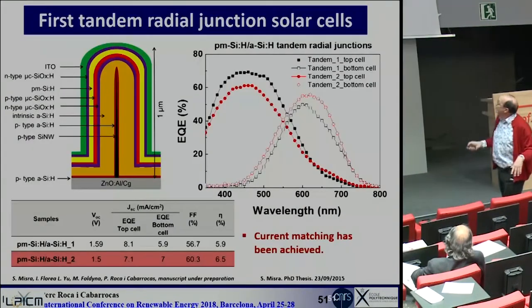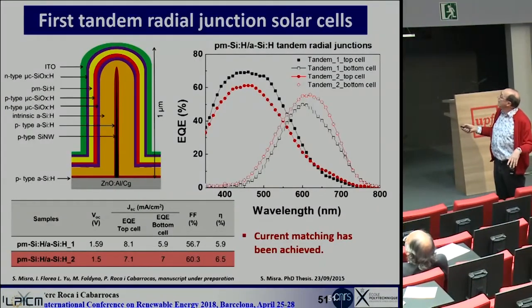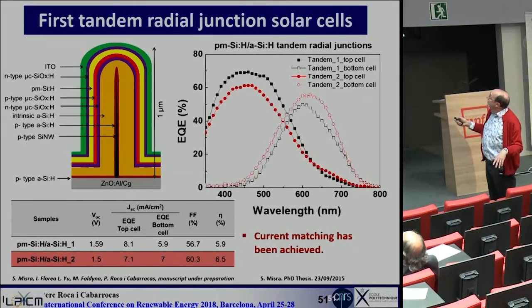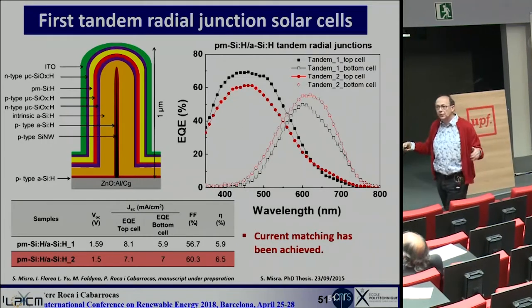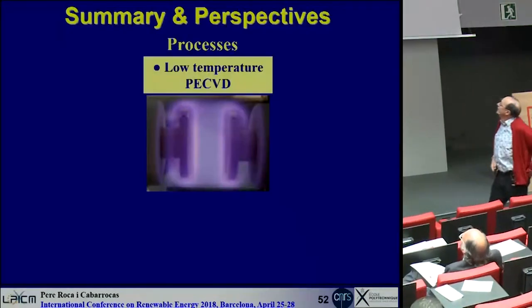And then when he did it, so that's the schematic, and that's the tandem solar cell, where you have the top cell, which in this case was amorphous, polymorphous and amorphous, but we can match the current from the top and bottom. You have it here, the current from the top cell, from the bottom cell, and we are adding the voltages of the two solar cells. So even in this structure, we can make a tandem device.